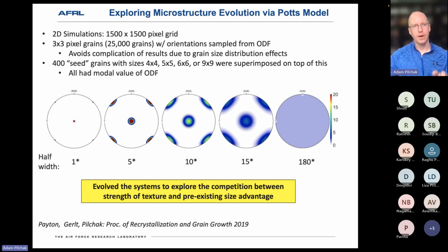So on top of this array of 3x3 pixel grains, we superimposed 400 seed grains, and these were the ones that would have size advantages. So we had seeds with 4x4 pixels, 5x5, 6x6, and 9x9, and those all had the modal value of the ODF. So they were all this rotated cube orientation. Essentially, they're probing the neighborhood effect with respect to misorientation, and then also the size effect.